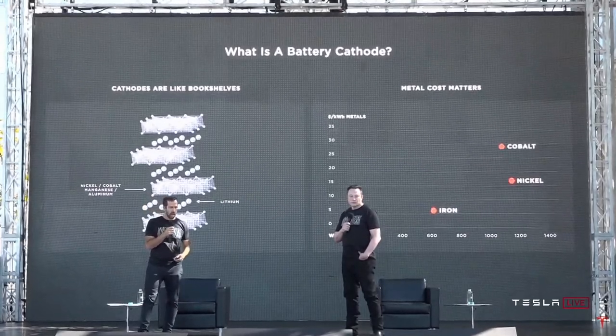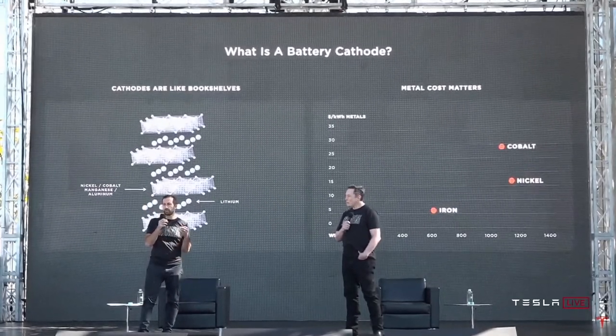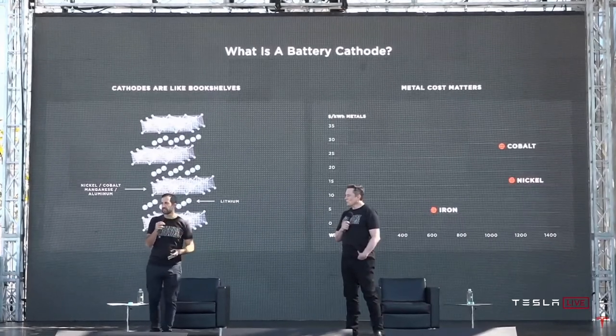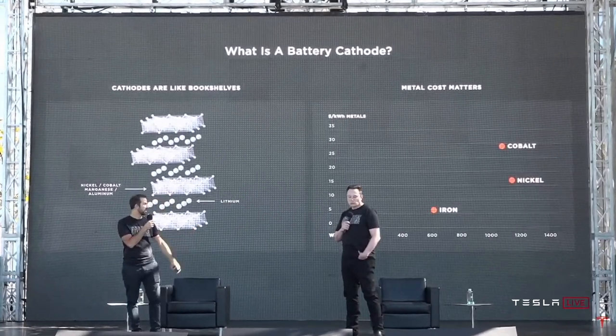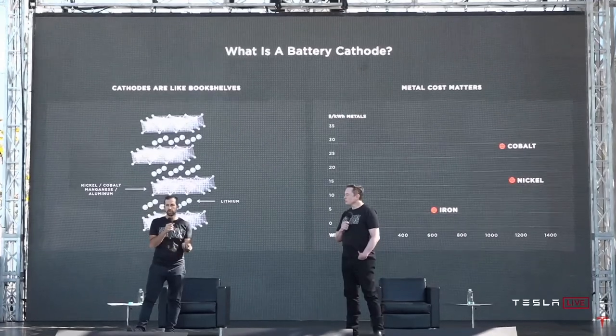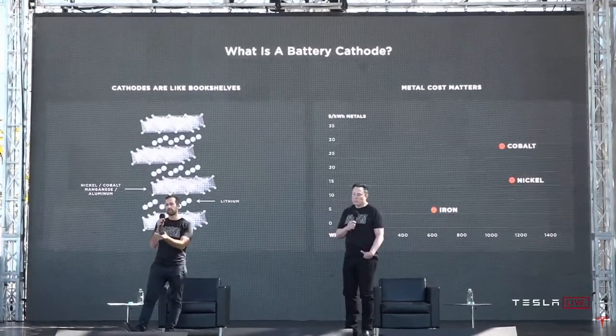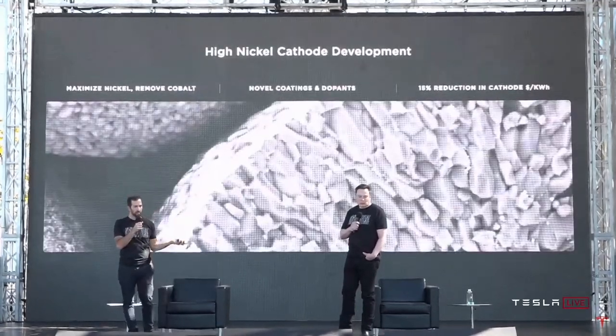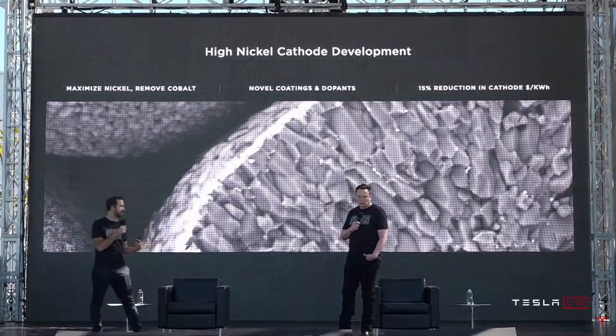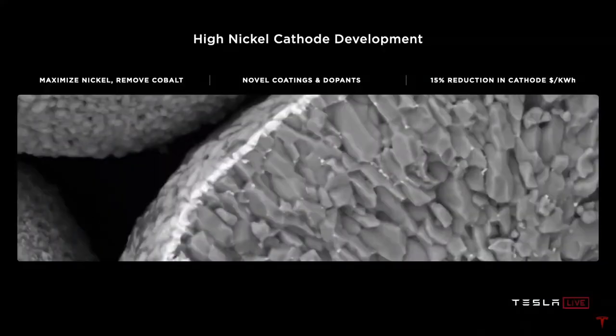But one of the reasons why cobalt is even used at all is because it is a very stable bookshelf. And the challenge with going to pure nickel is stabilizing that bookshelf with only nickel. And that's what we've been working on with our high nickel cathode development, which has zero cobalt in it, leveraging novel coatings and dopants, we can get a 15% reduction in cathode dollar per kilowatt hour. Big deal.